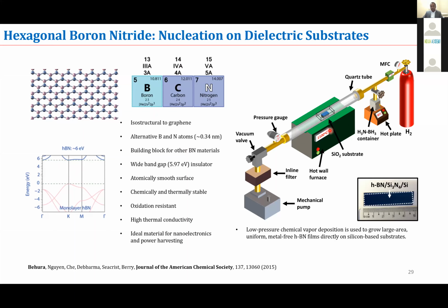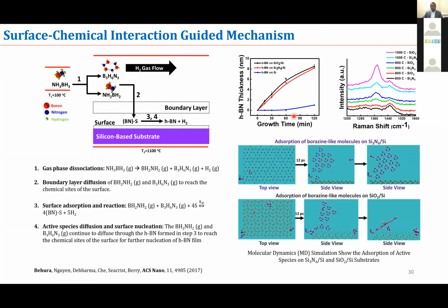So I followed a very similar process, where, because boron and nitrogen are the atoms in the boron nitride structure, I used ammonia borane as a precursor, which is a solid precursor, BH3NH3. And that breaks down to borazine, which is a benzene kind of structure. And then also there is a polymeric aminoborane.